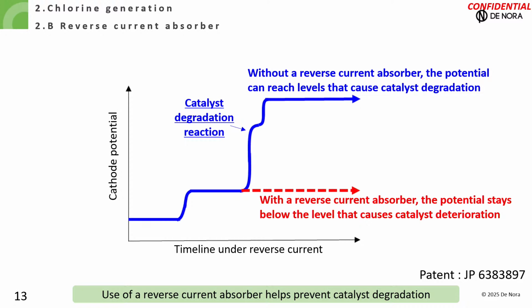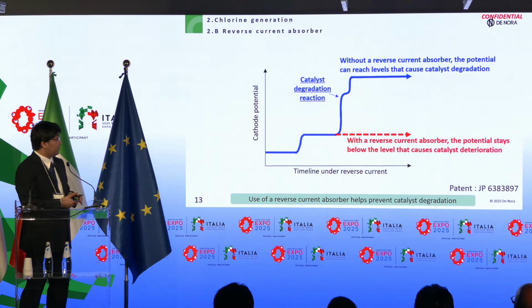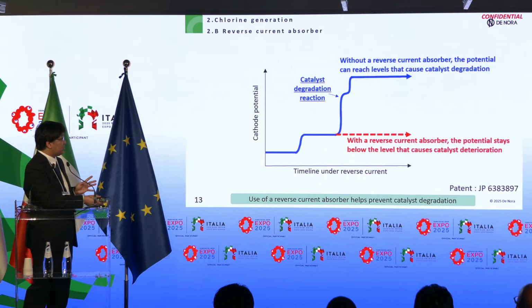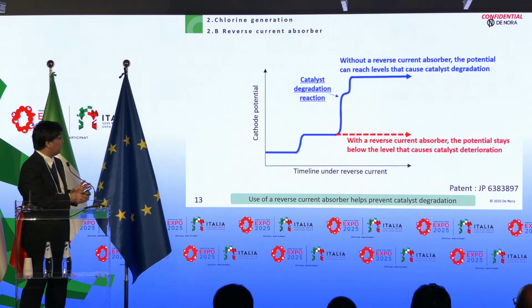In case of no reverse current absorber, the potential will shift to the catalyst deterioration reactions. But if enough amount of reverse current absorber is introduced, the potential stays at the redox reaction of the reverse current absorber and does not reach the catalyst deterioration reaction. So we can prevent catalyst deterioration by the reverse current absorber.